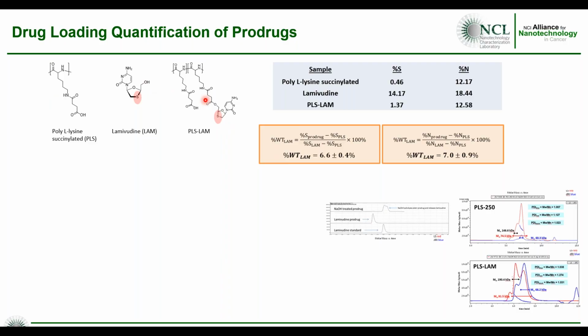We ran this through our CHNOS analyzer, and we looked at the sulfur content as well as the nitrogen content. In this example, our drug contains sulfur, so we can use sulfur content alone to assess drug loading. If you're working with a drug that doesn't have sulfur, you can always use nitrogen. But in this case, you need to run all the precursors. So you'd have to run the starting polymer backbone and the free drug by itself, along with the actual prodrug. And then through mass balance, you can basically calculate the weight percent of drug loading in your sample.